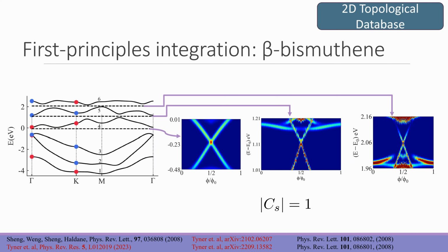And what we saw was really nice and very clean and in nice agreement with what we were seeing in our tight binding models, and allows us to almost right away say that the magnitude of the spin Chern number here should be 1, not 3, because we have a single Kramer's pair. And one thing I want to emphasize is that this calculation was actually pretty efficient. It was more efficient than if we were trying to identify a preferred spin direction, compute this complicated projected spin operator, and do a further calculation in the bulk under periodic boundary conditions, in momentum space.